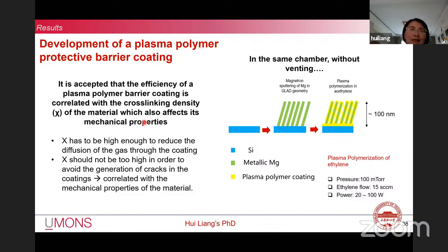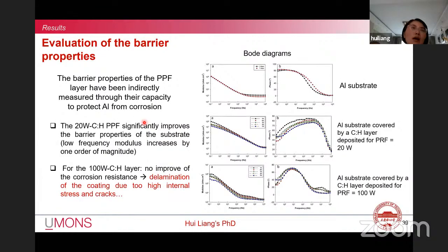the cross-linking density of the coating is related to its internal stress, and should not be too high because we must avoid the generation of cracks in the coating, correlated with the mechanical properties of the material. The evaluation of the barrier properties. The barrier properties of the plasma polymer ethylene layer have been indirectly measured through their capacity to protect aluminum from corrosion, by the corrosion resistance analysis.